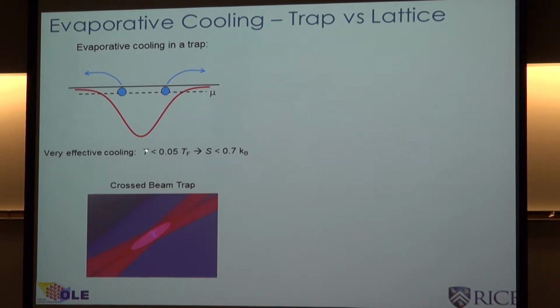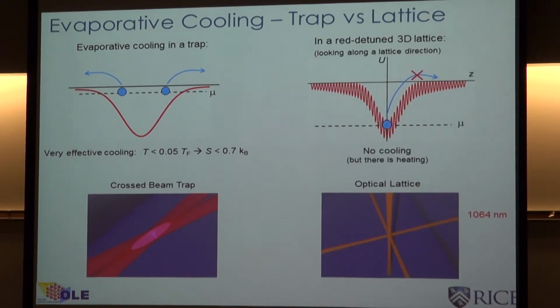In doing so, you're able to cool Fermi gases to below about 5% of the Fermi temperature, and that's kind of state of the art. In terms of entropy, that turned out to be something like 0.7 kB. So you realize that's already getting very close to the entropies that you need from the previous slide that I showed. Now, in a lattice, unfortunately, it doesn't work that way.